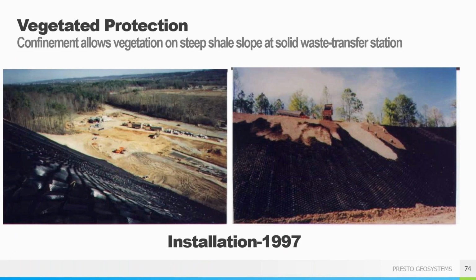While not a landfill, landfill design principles were used. Finally, a project from 1997 that does not involve a geomembrane, but rather preventing erosion of a 200-foot high slope at 1.5 to 1, and the slope was basically shale. This is at a solid waste transfer station in Jefferson County, Alabama. Other solutions were looked at, such as riprap, which was too expensive, and building a retaining wall at the bottom of the slope to collect the inevitable erosion, which would require too much maintenance. Eventually, the solution that was selected included a 4-ounce non-woven geotextile to provide separation and an in-plane drainage layer, and then 3-inch topsoil-filled GEOWEB panels.